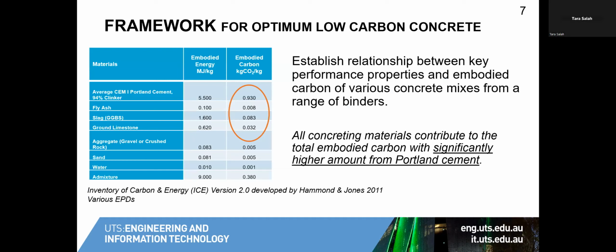To do this, we look at the embodied carbon of the concreting materials. And very quickly, this value may differ from place to place. But I think what is clearly important is that Portland cement is responsible for the highest amount of carbon dioxide per kilogram of material, roughly 0.93 kilogram CO2 per kilogram of cement used.